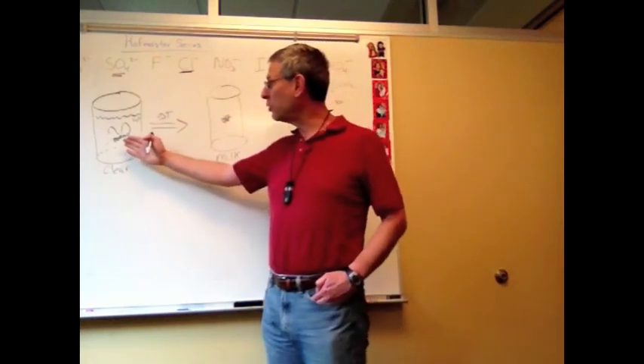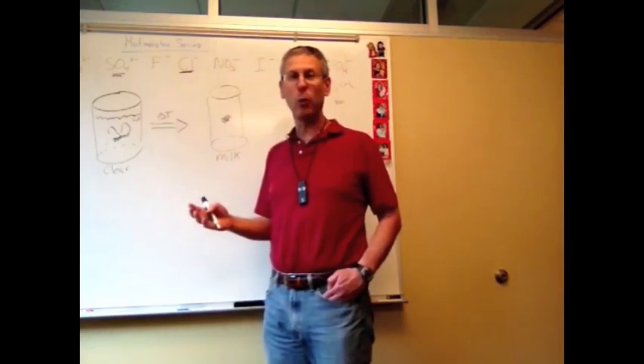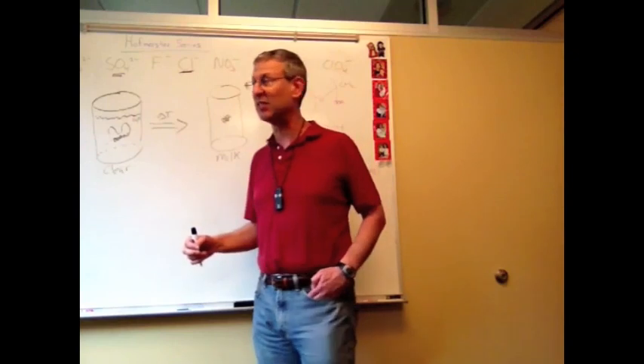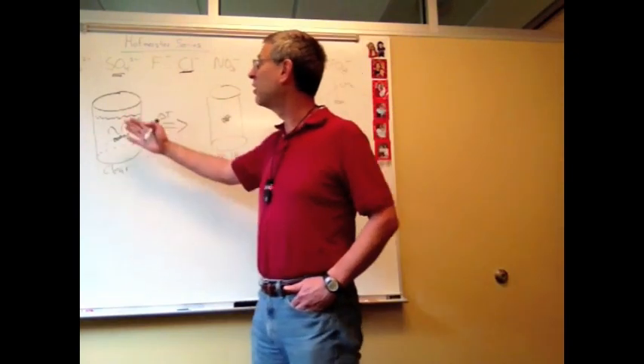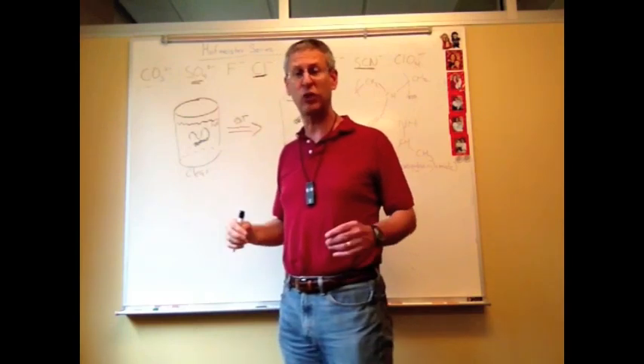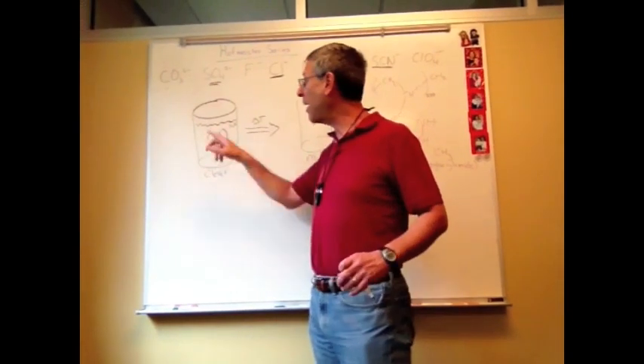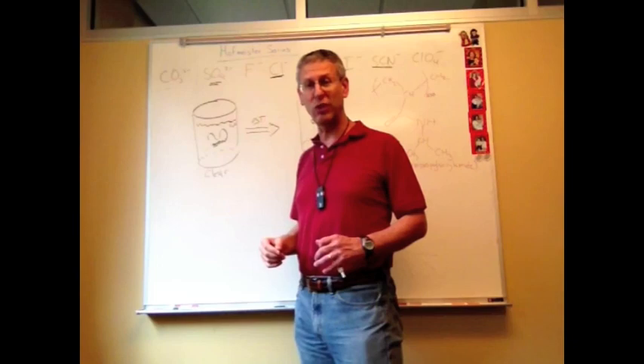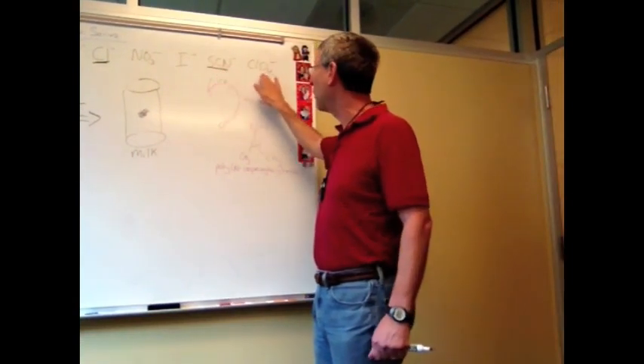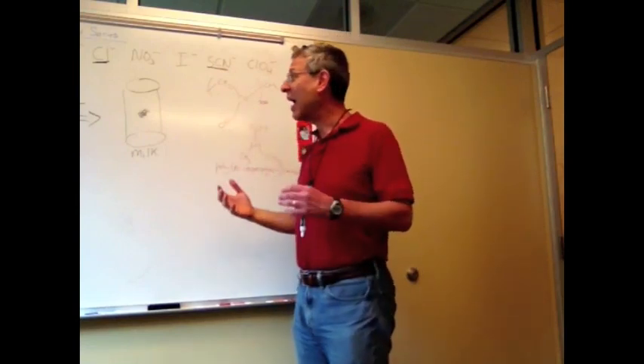Interestingly, when you add salt to the solution, the behavior becomes quite interesting. It obeys something called a Hofmeister series, first studied by Franz Hofmeister in the late 1880s. Here I'm showing you a series of anions. I have carbonate and sulfate on one end—these are well-hydrated, two-minus ions. They hydrogen bond with waters around them and jealously guard their hydration shells, the waters directly bound to these anions in aqueous solution. On the other side of this series, we have thiocyanate and perchlorate. These have charges of minus one. They don't guard their water molecules so well and are much less hydrated.